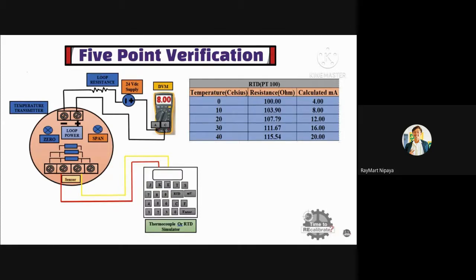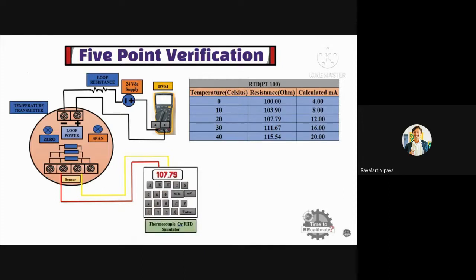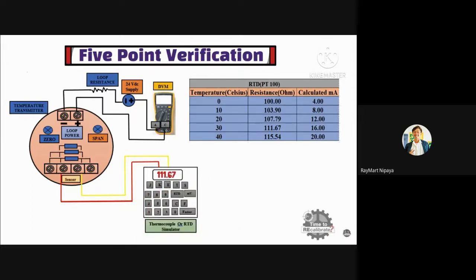After this, apply 107.79 ohm resistance value to the transmitter, and check the value in the DVM. The measured value should be 12 milliamperes. Now, set 111.67 ohm resistance value in the simulator, and feed this value to the transmitter. The DVM should give a 16 milliamperes value.